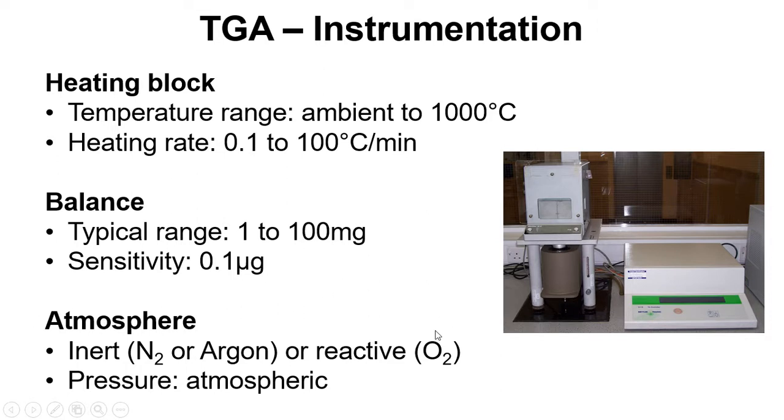The atmosphere we can control depending on the gas that we flow through our instrument. If we want something inert we could use N2 or argon; if we want something reactive we could use O2 oxygen or another gas. The pressure of the system is just atmospheric pressure, so there's no facility to control the pressure.